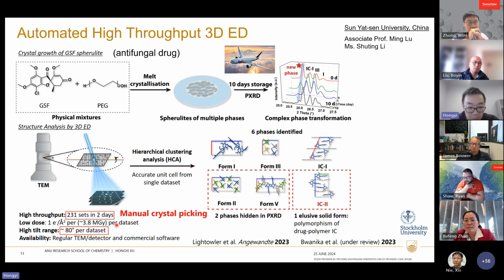So this is the new polymorph of a drug-polymer inclusion complex. Right, so I'm putting manual crystal picking here in red because, as I said before, if we really want to do phase analysis, we have to get rid of the ambiguities in picking, right? This is time consuming, and also it introduces bias because as humans, we usually pick things that look pretty and that we think are going to diffract really well, right? So we really want to get rid of this and look at everything that is on the grid. First, make sure that what we put on the grid represents our sample, and then we look at everything across the grid to make sure we don't have any biases. Only then can we start to do the quantification.